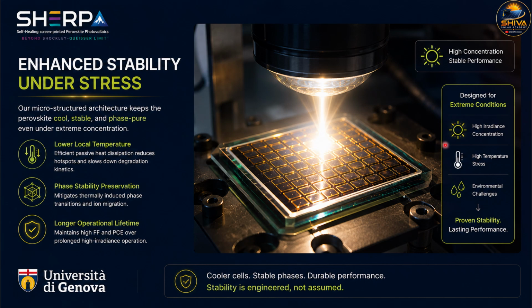The first key advantage is lower local temperature. By improving passive heat dissipation, we reduce hotspot formation and slow degradation kinetics. Second, we preserve phase stability. Lower thermal stress helps prevent phase transitions and ion migration inside the perovskite layer. And finally, this leads to longer operational lifetime while maintaining a stable fill factor and power conversion efficiency over time. So the main message of this slide is simple. Stability is not accidental. It is engineered through geometry, thermal management, and controlled light.